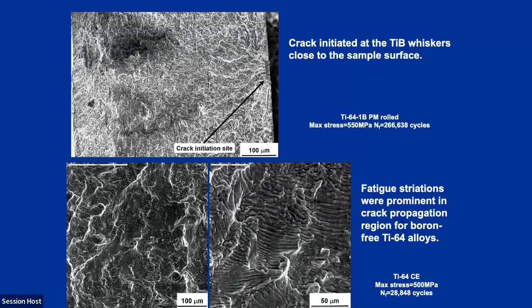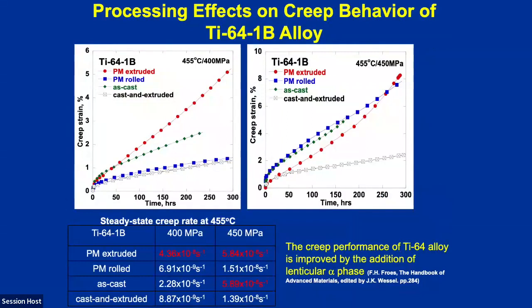In terms of the creep behavior, again, we looked at 455 degrees C, and we looked at 400 megapascals for our applied stress in this case, and 450 in this particular case. And these are just one-off tests. We did a bunch of tests, but I want to show you these representative ones. The first one is the cast and extruded. That one had the best creep resistance. Then it was followed by the PM rolled.